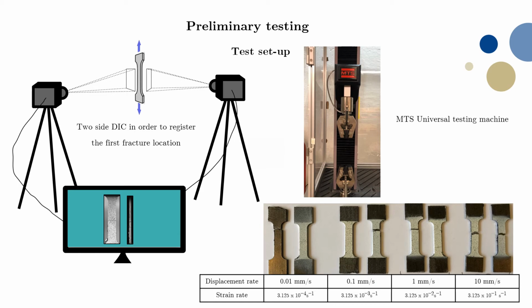From the first test, it was noticed that the fracture location was hard to capture with only one DIC camera, because the fracture could occur at the front surface and it was not visible in the opposite surface. So it was decided to use two-side DIC in order to register both the front edge and the side edge, and to be sure to capture the first fracture location.